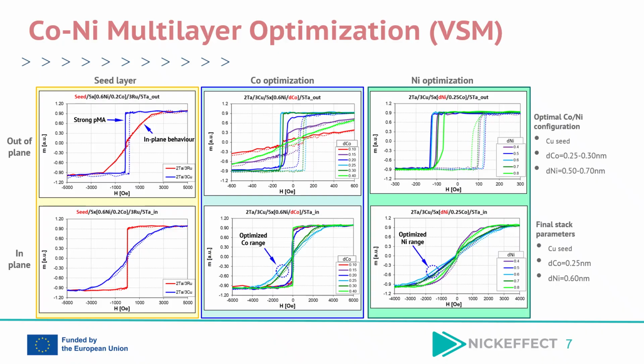The strongest PMA and the most favorable switching characteristics are observed for cobalt thicknesses in the range of 0.25 to 0.30 nanometer. The right column shows the nickel thickness optimization performed for a fixed cobalt thickness of 0.25 nanometer. The optimal magnetic properties are obtained for nickel thicknesses between 0.5 and 0.7 nanometer. Based on the VSM optimization results, a multilayer system with 0.6 nanometer nickel and 0.25 nanometer cobalt was selected for the next experiment.